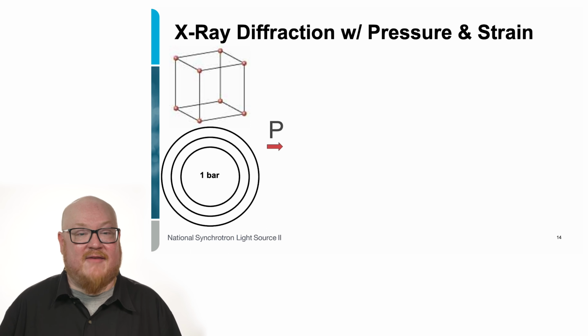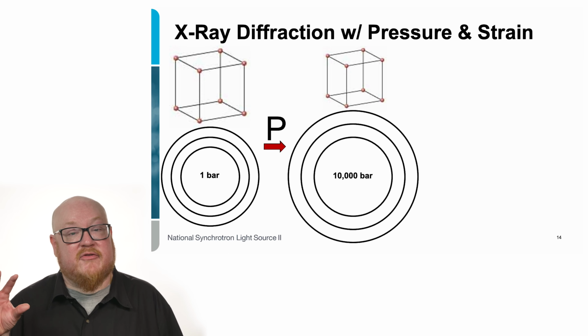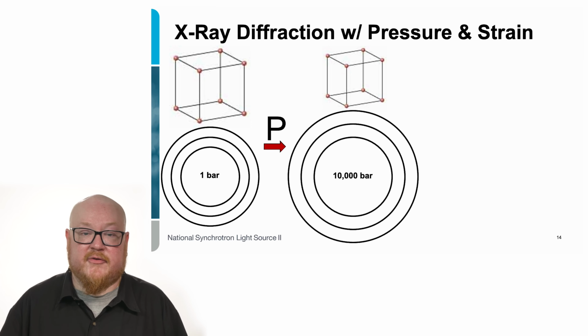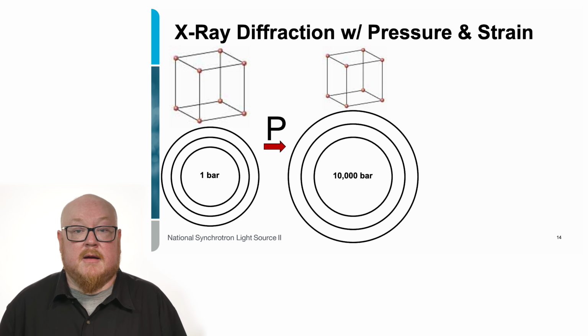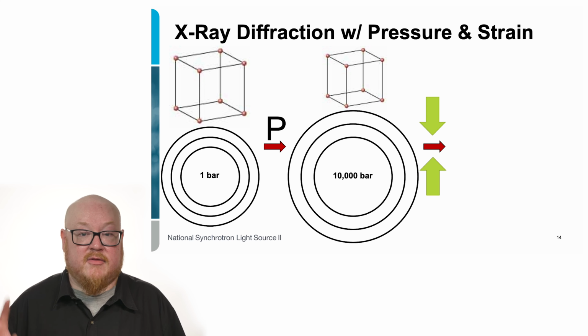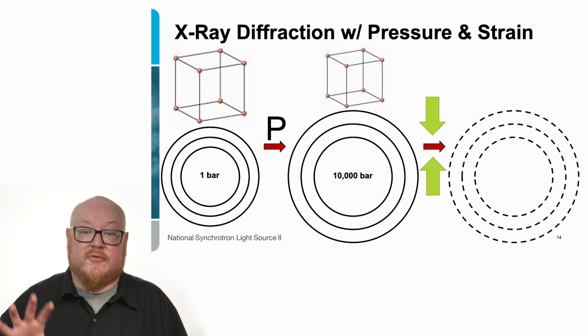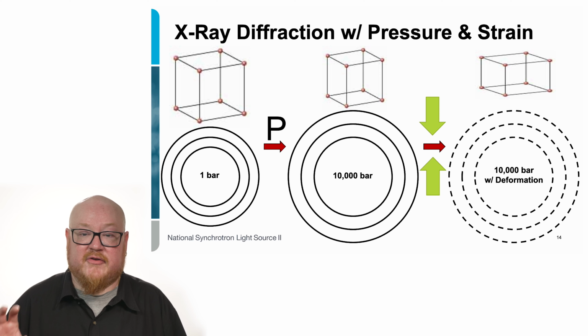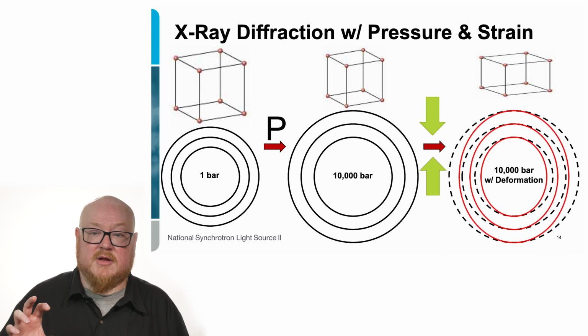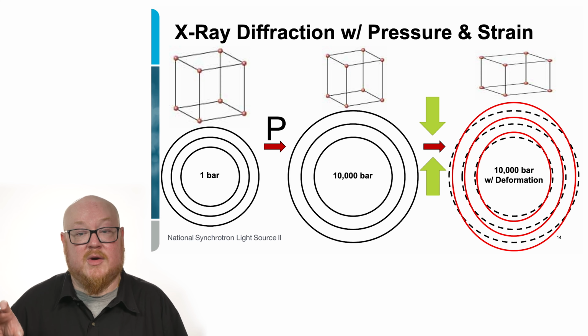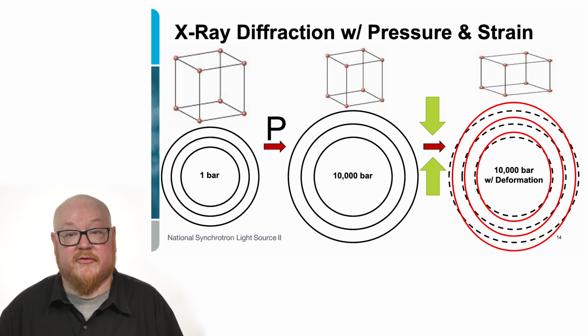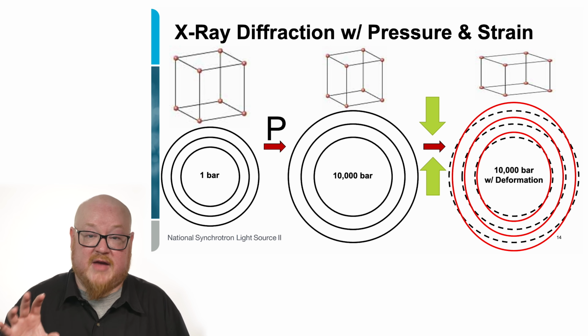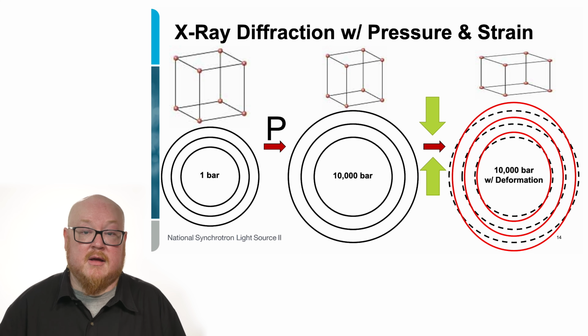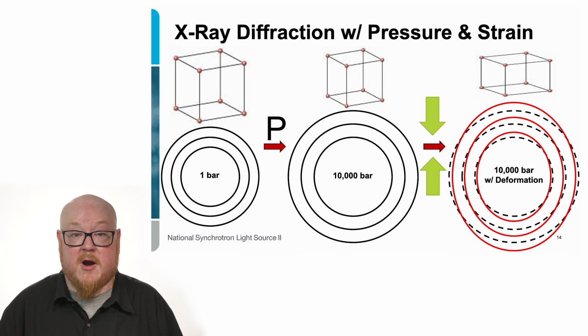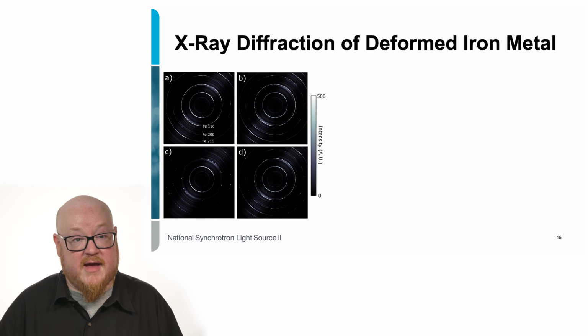Now, we're going to add some pressure. So we're going to make the sample smaller. We're at 10,000 bars now, and that causes the rings to get a little bit bigger. Now, once we add that deformation field, those rings that started out as nice perfect circles at 10,000 bars, once they've been deformed a little bit, those rings expand into ellipses. They're no longer perfect circles, and the sample is no longer the same shape as it was before we started. So this is what we're looking for in the experiment. And that's exactly what we see.